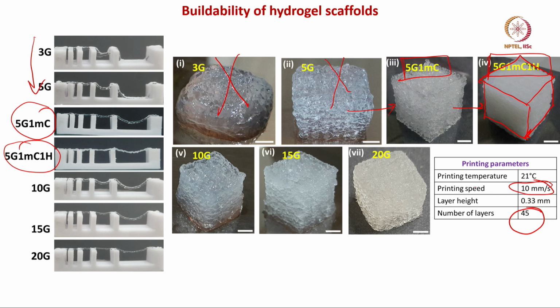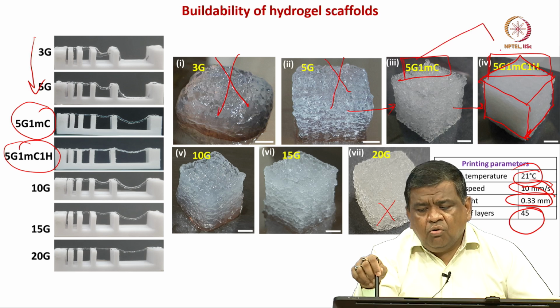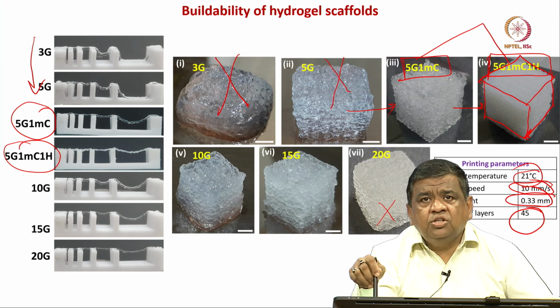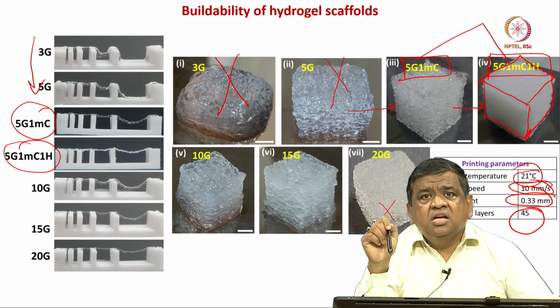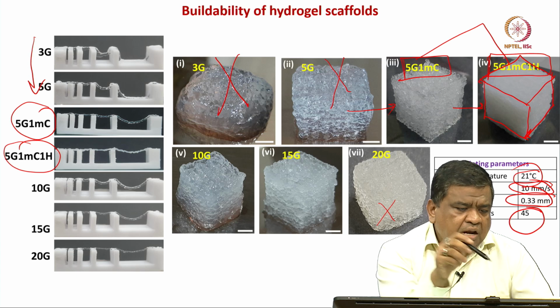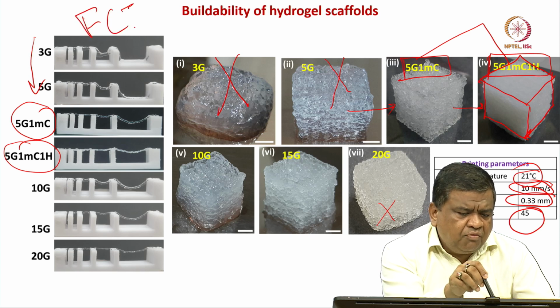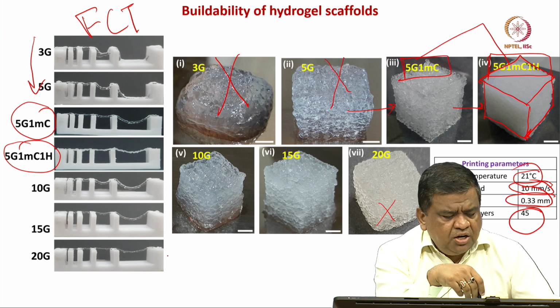The printing speed is 10 millimeter per second, each layer height is 0.3 millimeter, and printing temperature is 21 degrees Celsius. So, 3% Gelma is no good, 20% Gelma is good, but I do not think printing resolution is that good. As I said, our motivation was to work on the intermediate or low concentration of Gelma, and we demonstrated that in the low concentration of Gelma also you can build shape fidelity compliant structures, that is important.